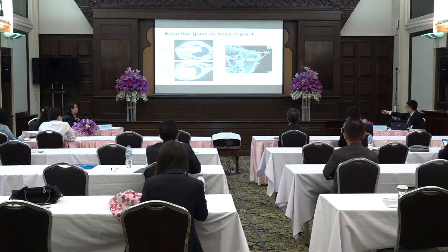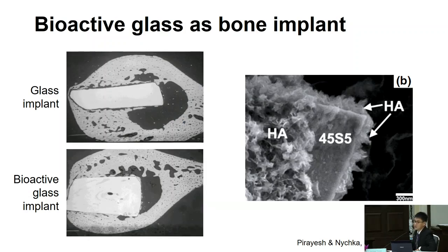And when we zoom in, 45S5 is the formula name of the bioglass. You can see the formation of this crystal that we call hydroxyapatite, which is a form of calcium phosphate found in the bone. This is from a research review in 2013. So the bioactive glass in the implant structure can allow the formation of calcium phosphate at the interface between the bone and the glass. So this reduces the rejection of the implant.